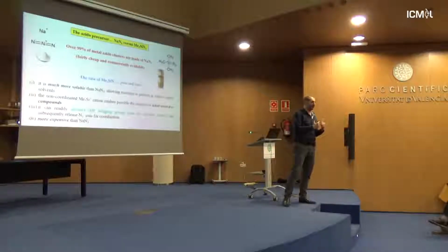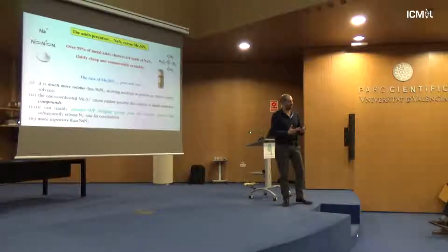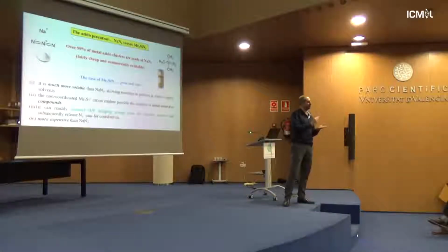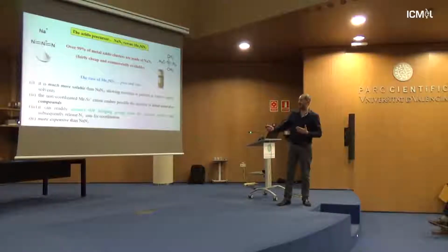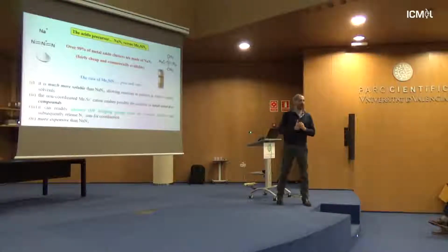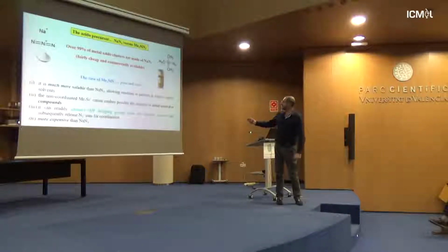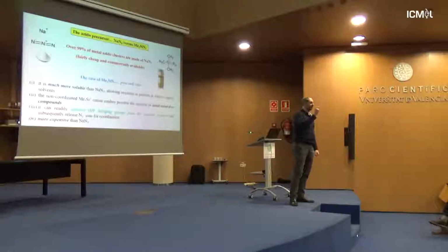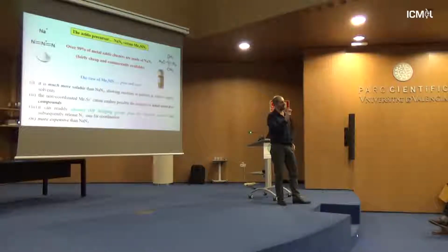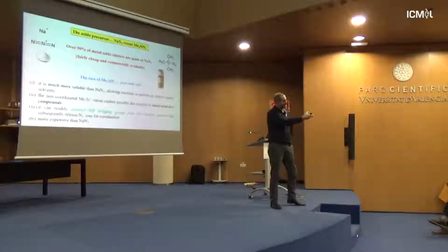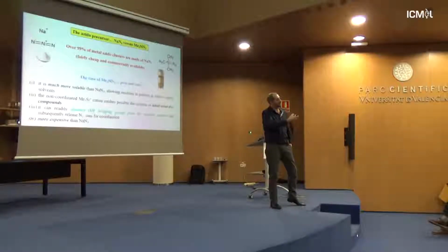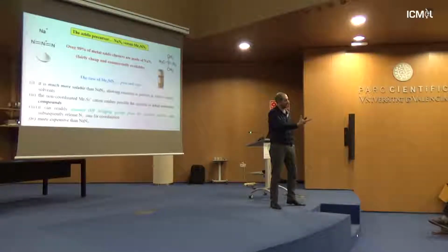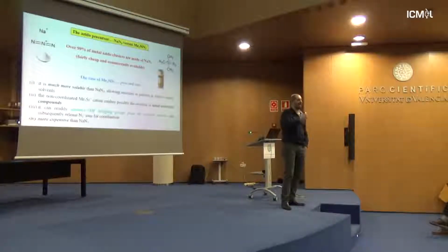What does that mean? For us, the synthetic chemists, that means that this allows us to perform reactions in many different solvents, something that is not really the case when you use sodium azide. Good. The second comes from the structure of trimethylsilyl azide. The trimethylsilyl cation here is not chemically innocent like the sodium cation. The trimethylsilyl cation has the ability to remove or subtract hydroxides from the reaction solutions.